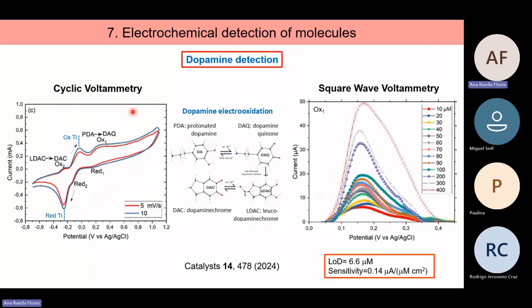Now we can focus on the oxidation 1 peak, and we can perform a square wave voltammetry by decreasing the concentration of the dopamine. We started with 400 micromolar, and we went down to 10 micromolar, and with 10 micromolar, we still were able to detect the peak. In fact, the limit of detection was of the order of 7 micromolar. If we want to go to lower concentrations, we have to use another technique.